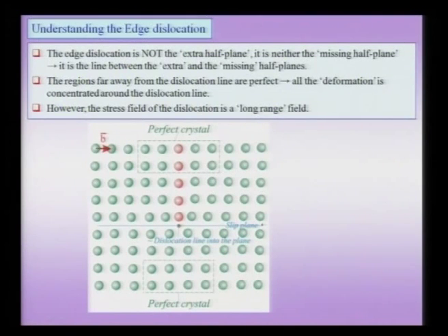And it could also be the influence of a free surface which is causing the dislocation to move. The minimum stress you need to exceed for a dislocation to move is what is called the Peierls stress or the internal friction stress, and the reason for this is very simple. When you look at an edge dislocation, for instance in a picture, if we go back here, it is in a metastable equilibrium state. It means that even though it costs energy for the crystal and this dislocation would like to leave the crystal, nevertheless it is locked in a small energy minimum, a small valley.